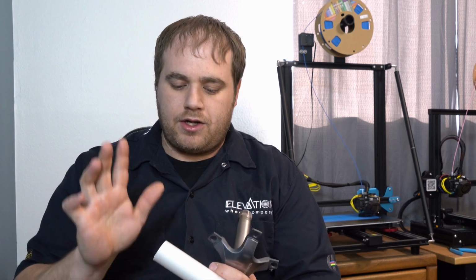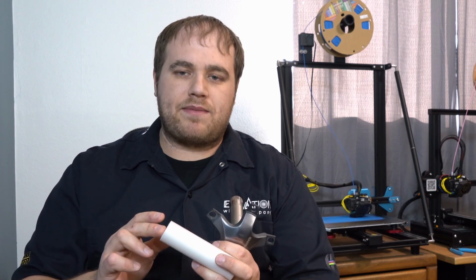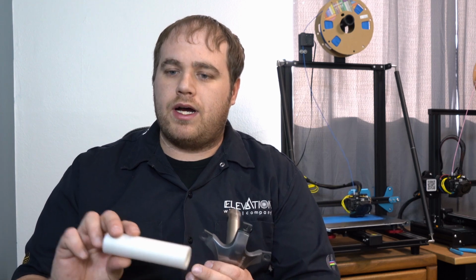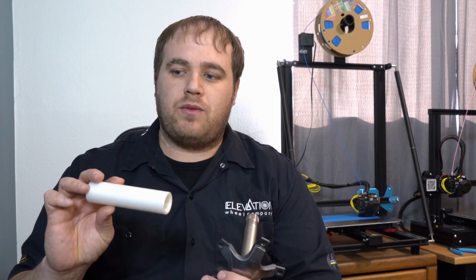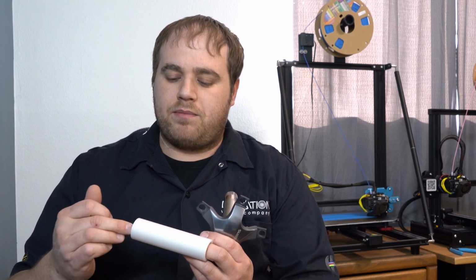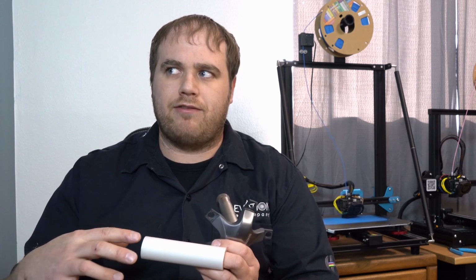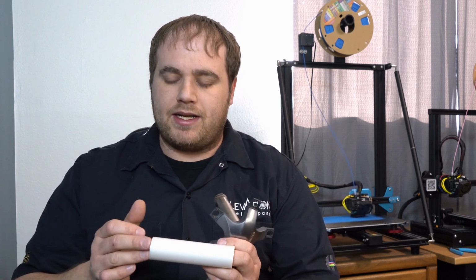And then when you're printing with this, also look up the specs. It's kind of picky about build surfaces. What I ended up using was a PEI sheet with Dimafix to bond everything to it. And then I printed it all on a raft, and I made the raft quite a bit bigger than normal. I made the raft about 35 millimeters big to help it adhere.